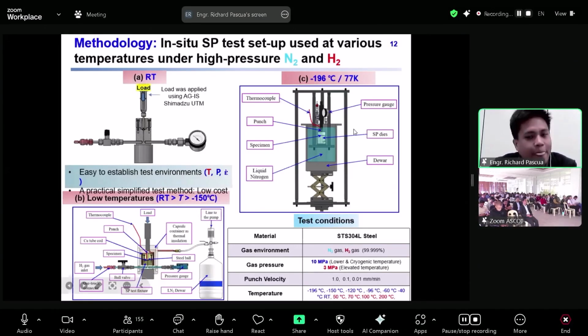For the test conditions we used for the experiment, in the case of the gas environment, we used two different gases, nitrogen and hydrogen, in which the hydrogen gas was used to assess the HE susceptibility, or hydrogen embrittlement susceptibility, of the material exposed to the hydrogen gas environment.